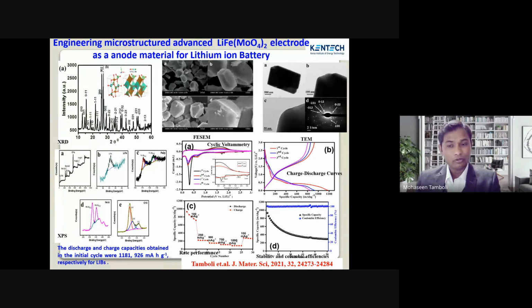It shows the oxidation states match with the material which we have developed, and all the elements are present here: lithium, iron, molybdenum, oxygen. Furthermore, we have studied this material for lithium ion battery, and when we check the charge discharge capacity, for the first and second initial cycles, it shows high specific capacity, around 1100 and 926 milliampere hour per gram. That is almost threefold more than the commercially available graphite.